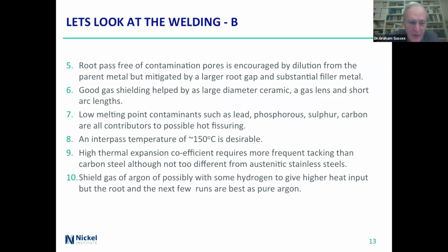Shield gas, argon, possibly some hydrogen to give you a higher heat input, but that'd only really be for the root, and the next few runs are probably best to be pure argon. You won't get quite the amount of heat, but still.